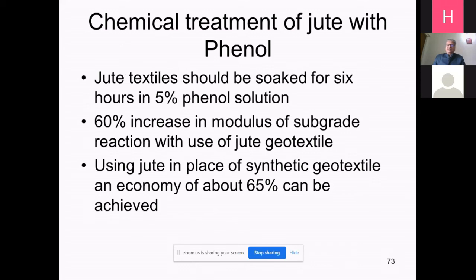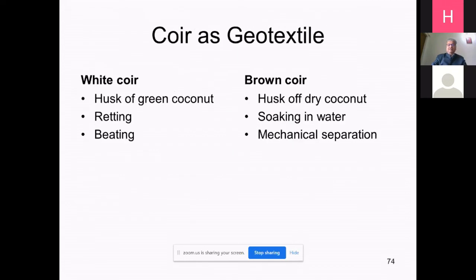But at the same time, if an excess amount of phenol is there, then due to the chemical reaction of phenol also, jute may degrade. So we have to make a balance between the minimum and maximum doses of phenol. This comes out to be a 5% phenol solution used for 6 hours, which gives the optimum result. With this, the K value, that is the modulus of subgrade reaction, increases by 60%. Using jute in place of synthetic geotextile, an economy of about 65% can be achieved.